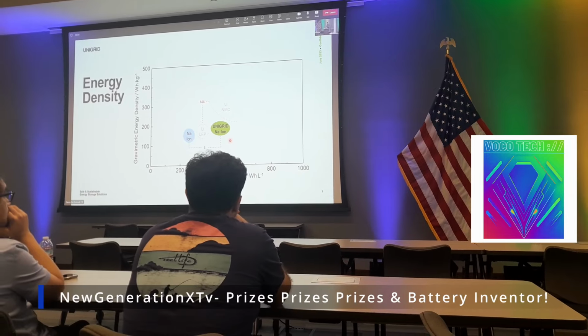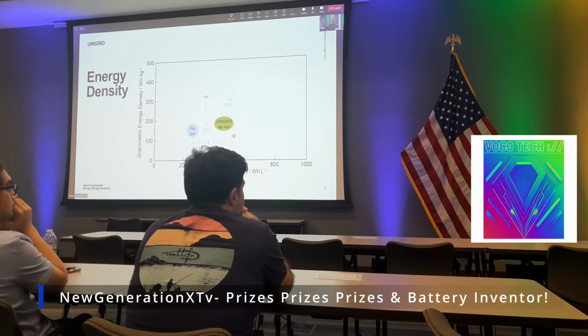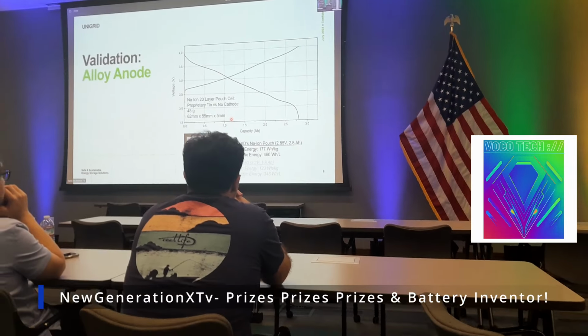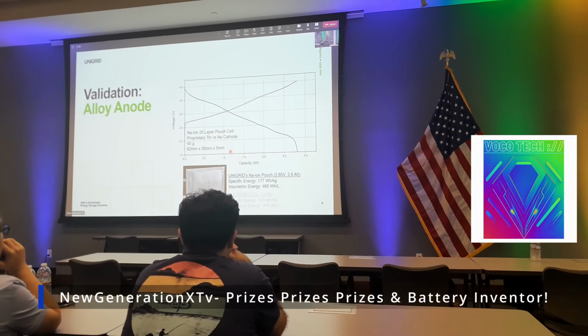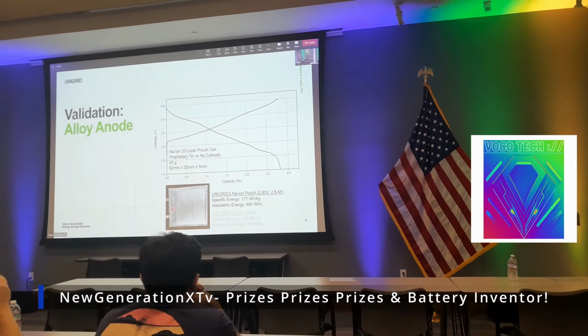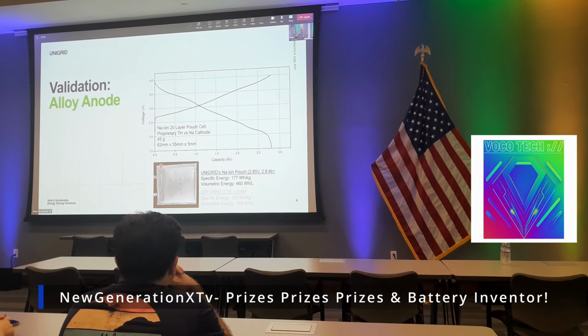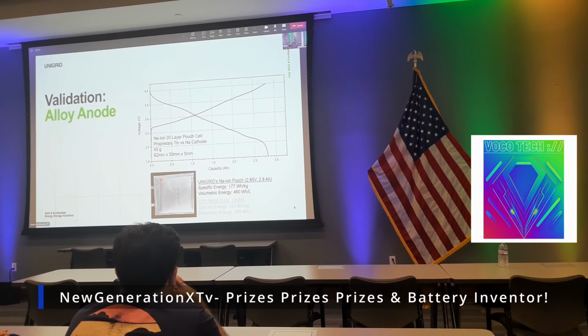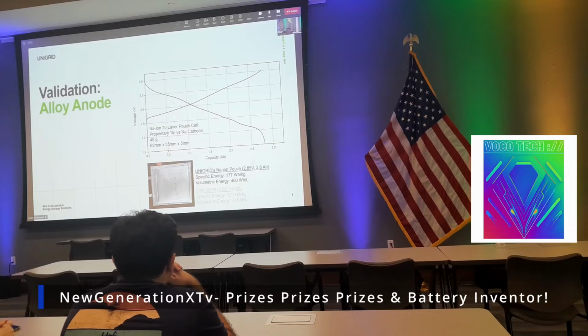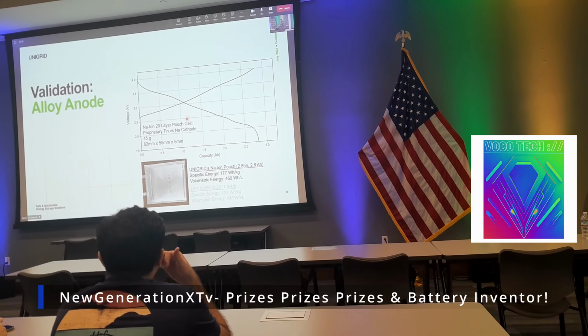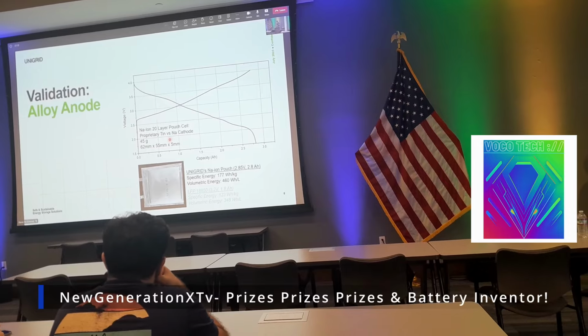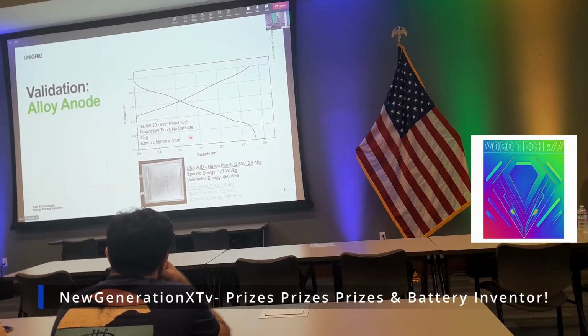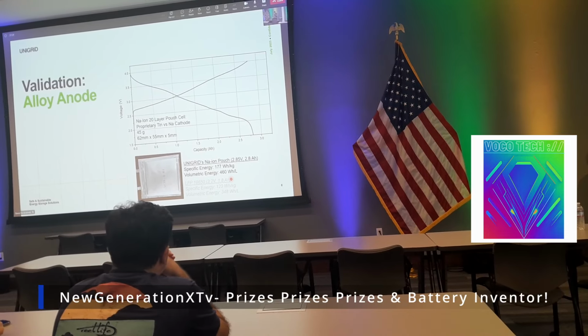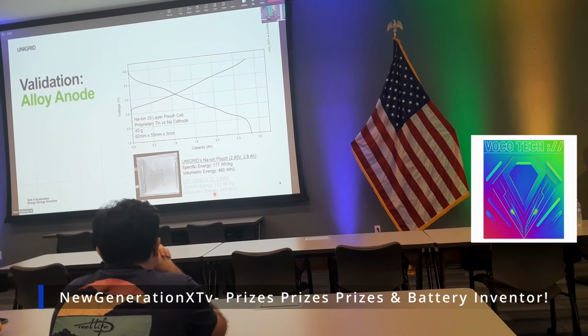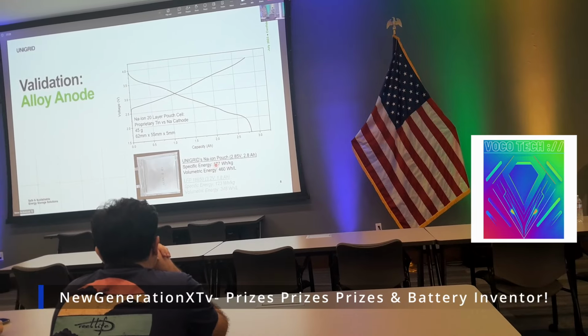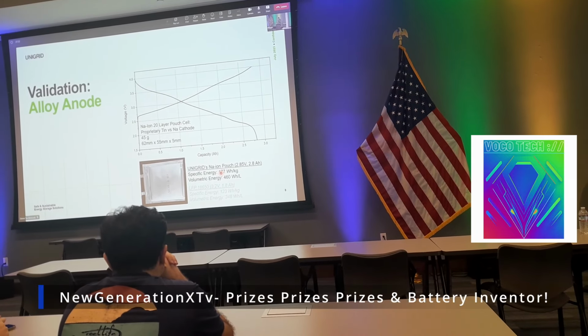This chart only shows a projection. Often we need to show that it's demonstrated and validated in the lab. So this is something we set out to do in the early days. We assembled a representative pouch battery cell that looks like this here. So this is the kind of battery you have in your iPhone. It's a very similar shape. It's rectangular in nature. It has about 20 layers of electrodes in there. It uses our proprietary tin anode and sodium cathode. And we show that the energy densities we can achieve here are significantly higher than your commercial LFP out there. So it's not just a projection, it's real. It can deliver what it promises to do.